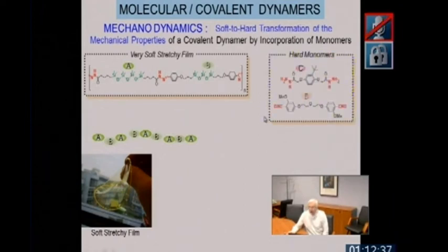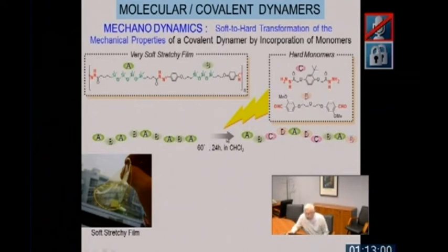But then you can think of taking a set of hard monomers, not so flexible as these ones. This has a phenyl ring, not flexible at all. And this has some flexible chain, but it's not so flexible as the silicones, as the dimethylsiloxanes. So if you take this and add it to this, then you will get a chain where you introduce these units into the new chain, and now these more rigid components will enter into the chain progressively as you add more and more of it.